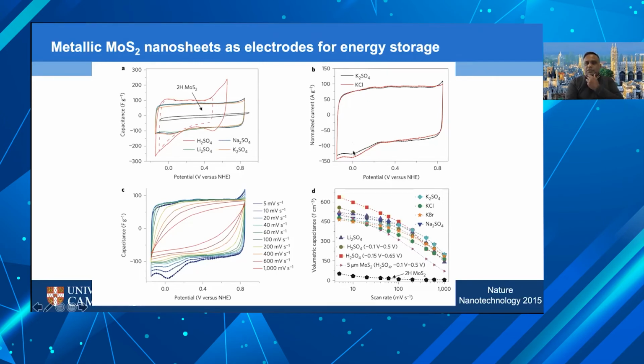What this plot shows is that it is in fact the positive cations that are intercalating and deintercalating. There's some question because in this plot we see that the anions are all the same. Are we getting this performance because of anion intercalation and not cation intercalation? The way to prove that is to keep the cation the same and vary the anion, and you can see that the CV curves are almost identical, suggesting that it's the potassium that intercalates between the sheets of 1T phase MoS2.